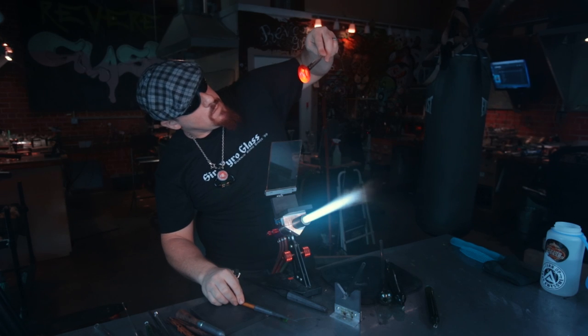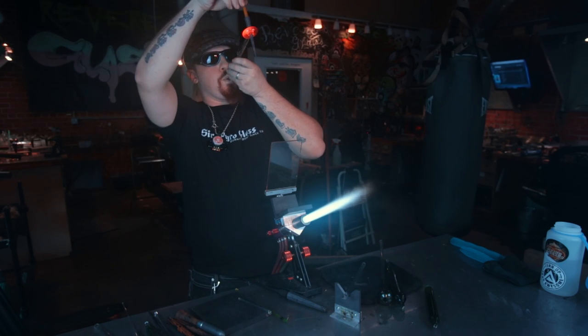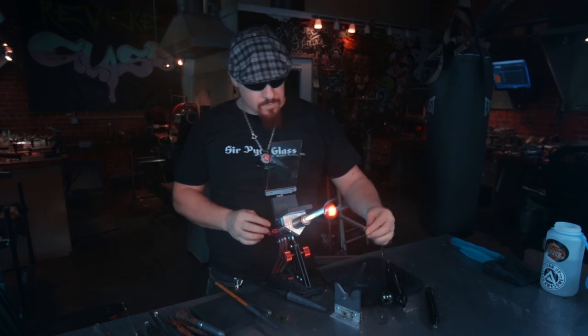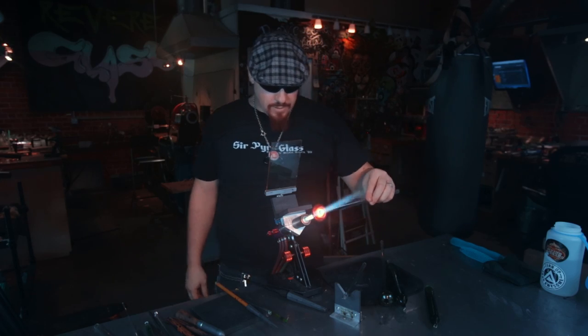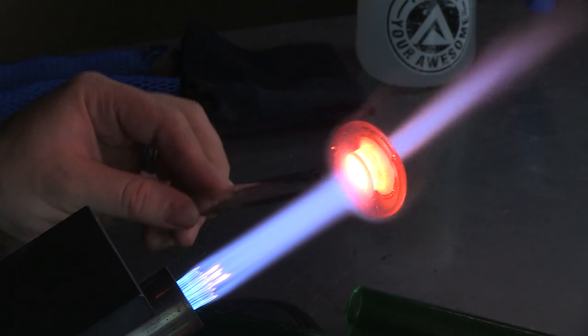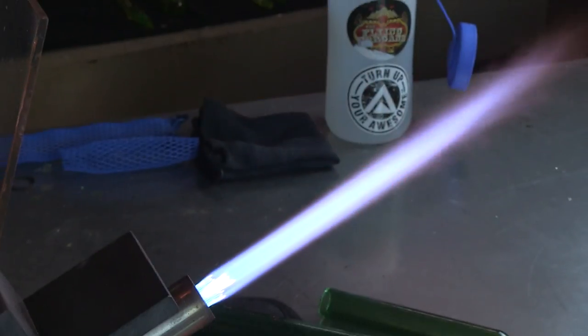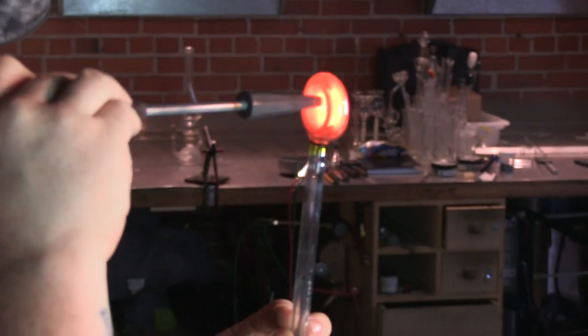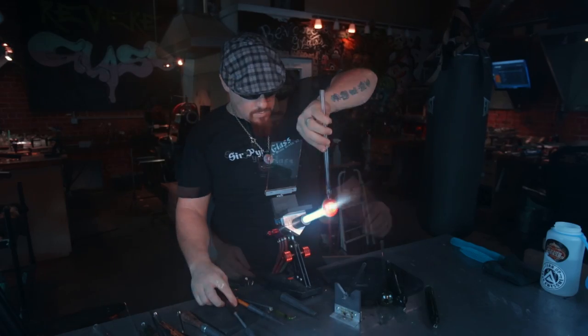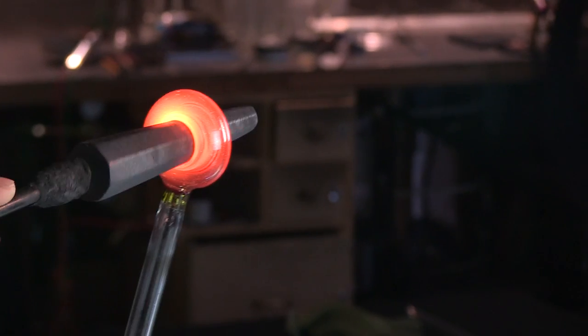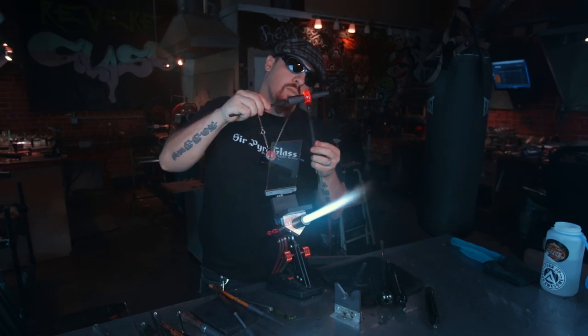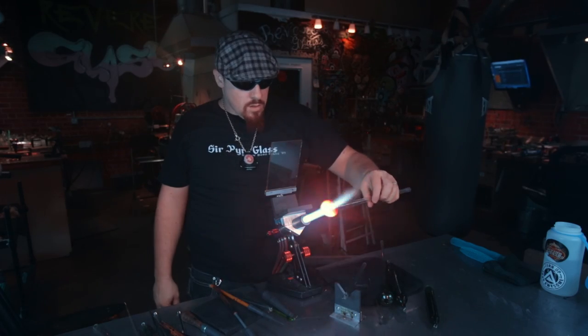Yeah, and you want to be really careful at this point to actually not let the outer wall get hot and keep its form. Like at any point with the glass, you want to keep a one solid state form that keeps your concentric round, and the outside of the donut at this point is what holds round. And you can tell that by looking at the heat and the gradient of the heat on the glass. The inside circle is much hotter than the outside circle.